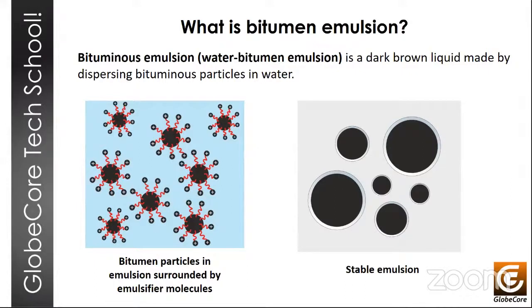So when this mixing process is stopped, the emulsion quickly breaks and bitumen particles can merge, and this is called coalescence. To keep the components mixed and to keep the emulsion stable, an emulsifier is introduced into the emulsion, and it is a surfactant that prevents or slows down the separation of these two phases.